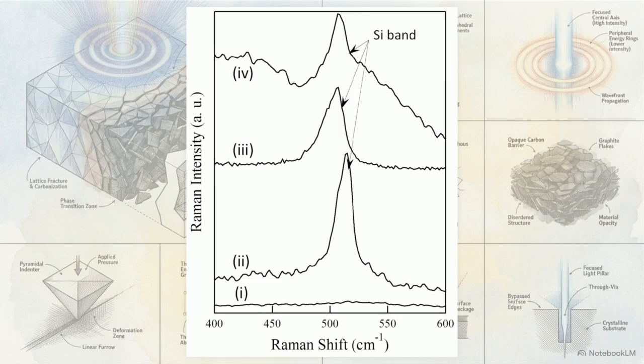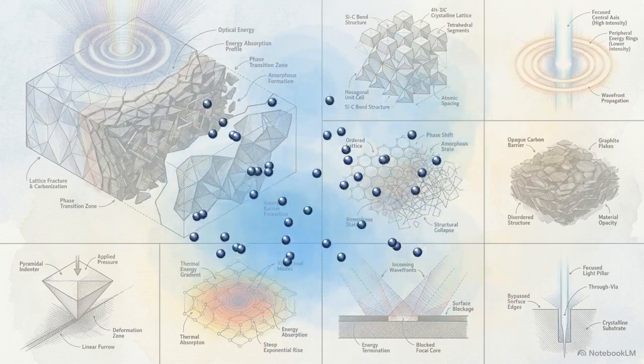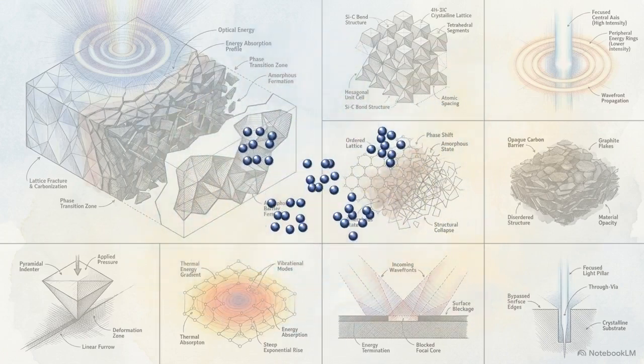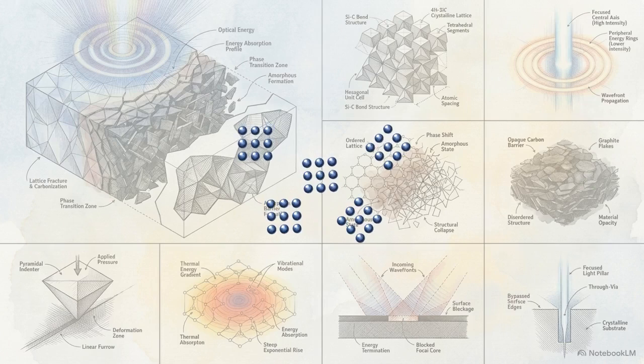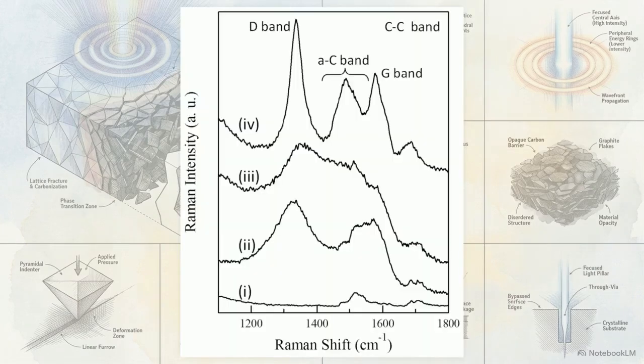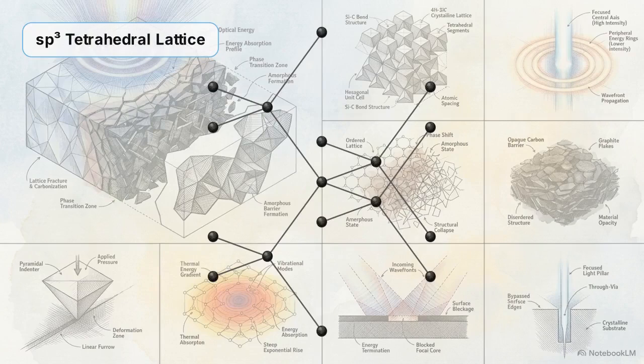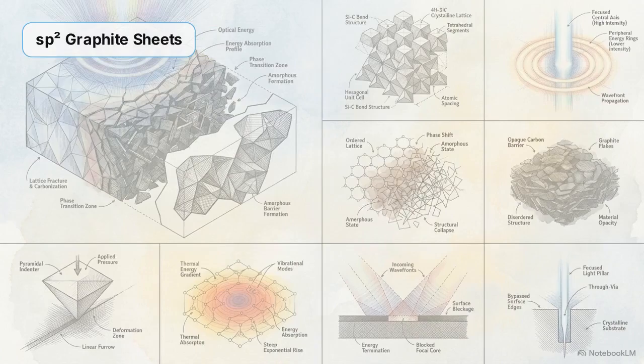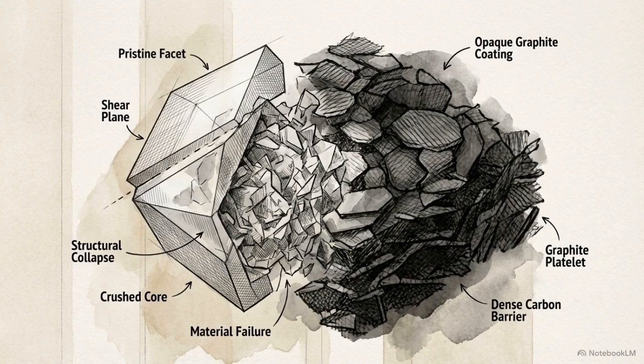Raman spectroscopy confirms the presence of the silicon component. A sharp silicon band emerges at approximately 500 inverse centimeters. The sharpness of this band indicates the formation of ordered quasi-crystalline silicon nanoparticles, rather than a disordered silicon blur. The carbon component is also visible in the scratch groove. Strong D and G bands appear between 1200 and 1600 inverse centimeters. These bands signal an sp3 to sp2 transition, indicating the amorphous carbon is transforming into graphite. Localized stress forces 4H SiC to segregate into a highly absorptive graphitic barrier.